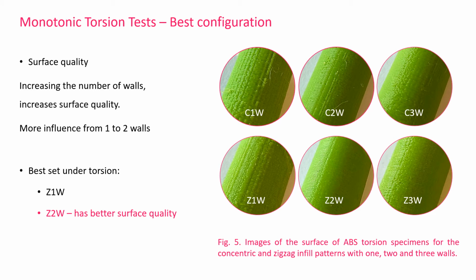It can therefore be concluded that the zigzag infill pattern with 1 and 2 walls proved to be the configurations with best performance under monotonic torsion loadings, with residual differences. Although the one-wall configuration had slightly better mechanical properties, the zigzag pattern with 2 contours was selected for the fatigue tests because it showed better surface quality.